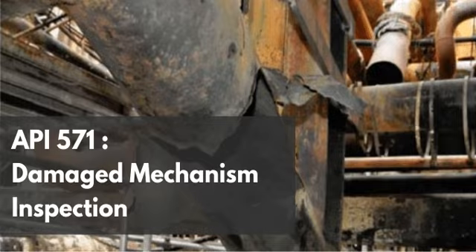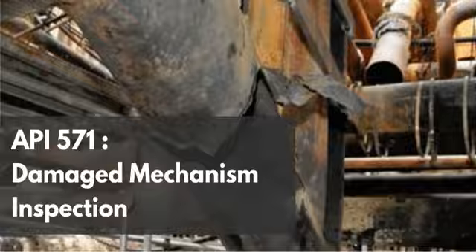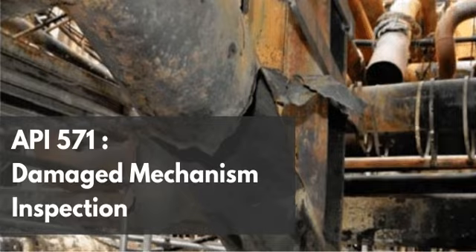They are running a furnace. Over time, the hydrocarbons flowing through the tubes start to thermally crack. They break down. Yeah, and they lay down a layer of solid carbon coke on the inside wall of the pipe. Now, that coke acts like a thermal blanket. Which is bad for heat transfer.